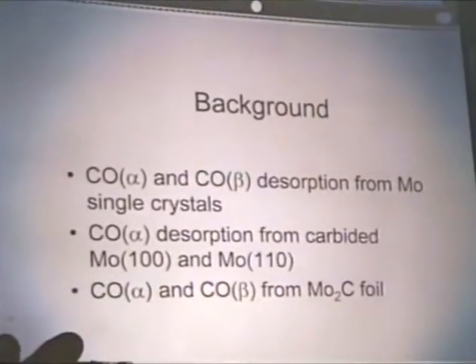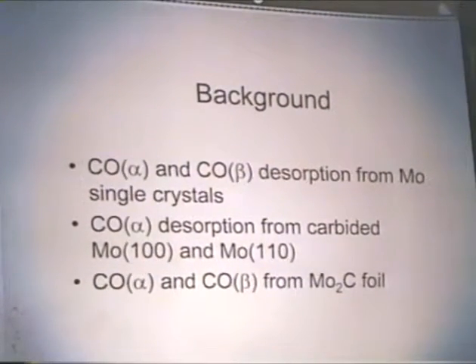And finally, a last case that I want to discuss is recent results by McGreen et al. on a moly carbide foil, where unfortunately they saw the opposite. They saw alpha and beta CO desorption from a moly carbide foil.